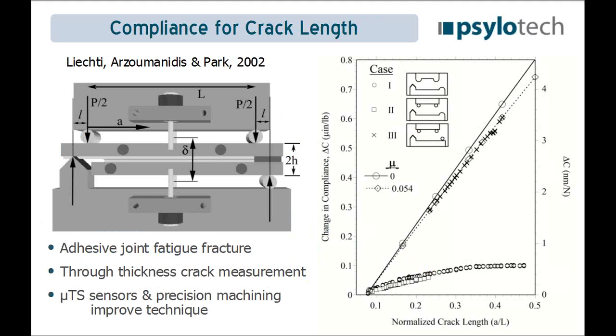Another interesting way to do it is to just use compliance of the specimen. In this particular case, this is the DCB sample that I used in graduate school, and we were able to track the crack length based on the displacement measurement and the force measurement. And you can see the crack length compared to the compliance. Theoretically, it's a linear relationship. You have to be very careful about friction at the contact points, but we were able to get it quite close with this kind of configuration with these 3 rollers and a triangular point. The triangular point was important because if we didn't have it, the specimen, it was a fatigue test, could walk on us. And as it rolled left to right, it looked like the crack was growing when in fact it was not.